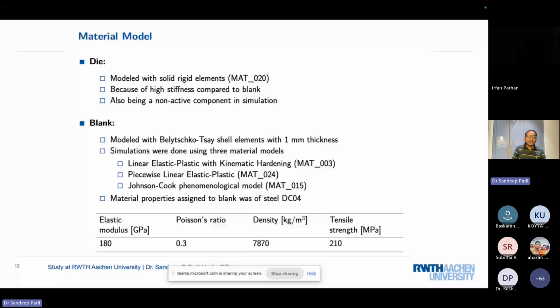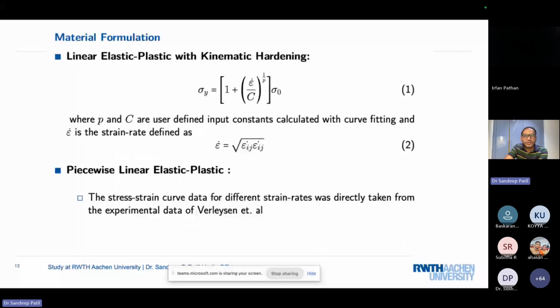So if you look at the kinematic hardening, which is a very simple model, I will explain it in a minute. The material properties we assigned to the blank were steel DC04, as I said, and the DC04 mechanical properties (elastic modulus, Poisson ratio, density, and tensile strength) are tabulated in the table. The first one is kinematic hardening, which is a very simple one. So a straight line and then going up, with some kinematic piecewise linear elastic plastic.